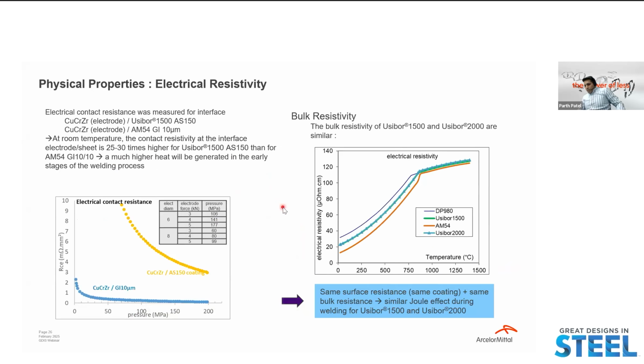Another myth is that people think the coating is different, so it's going to have different welding parameters. But Usibor and Ductibor have very similar coatings. If you look at this chart, we're trying to show electrical contact resistance for aluminum silicon versus GI coating. It's much more than GI coating - almost 25 to 30 times more.